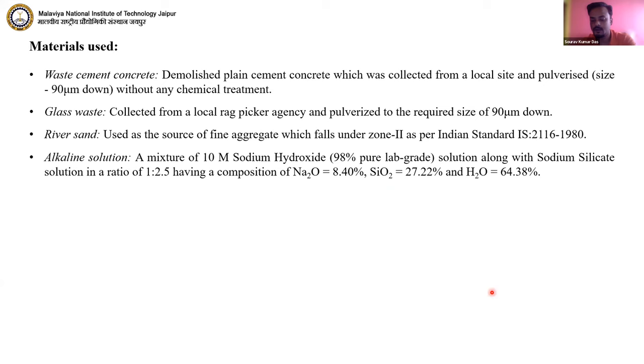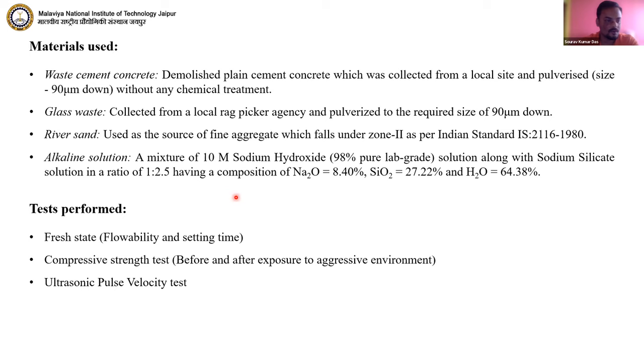So these are the different tests performed in this study. In the fresh state, we assess the flowability, where our mortar should attain 105% flow as per ASTM. And there is a setting time requirement also, because we are using two types of waste, so there's a combination effect on the setting time. And then we go for the compressive strength testing before and after exposure to the aggressive environment. We also did the ultrasonic pulse velocity test, which is an NDT test, gives us a basic idea about the density, and helps us calculate the modulus of elasticity.